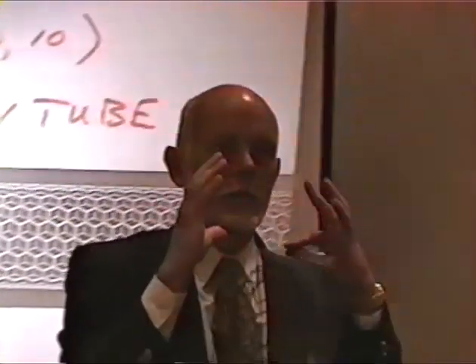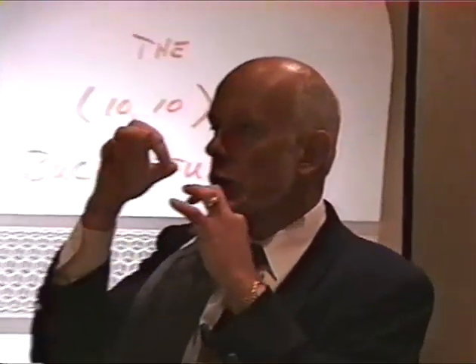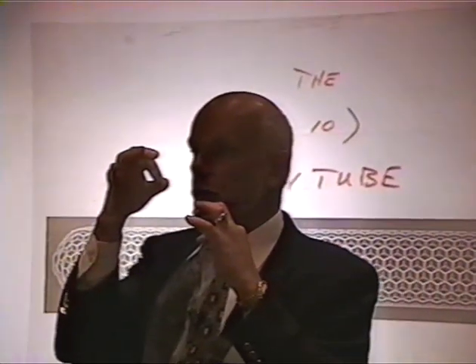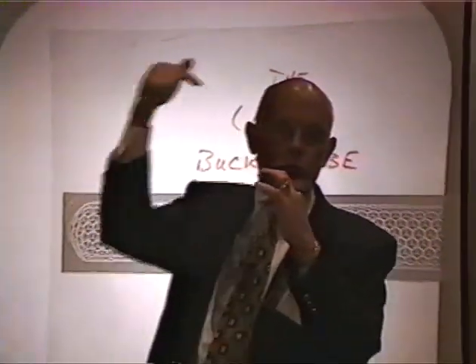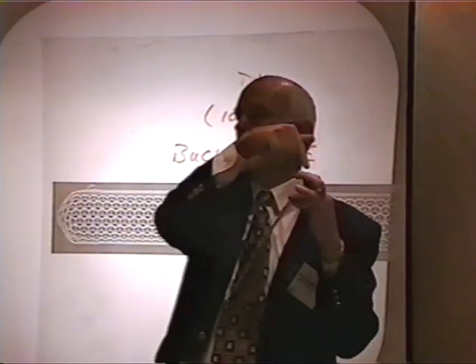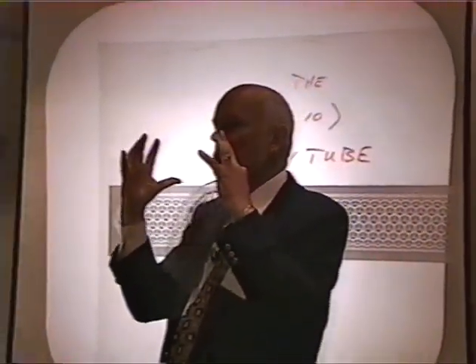C240, in its most energetically favored form, is a round buckyball shape with the pentagons, all 12 of them, separated apart from one another as far as they can possibly be, and that's done with perfect icosahedral symmetry. It turns out to be the next fullerene up from C60 that has perfect icosahedral symmetry and has the same relationship between the pentagons, namely to get from one pentagon to another, you go to a vertex and follow along the bond and you'll find the next pentagon. C240 is the next member up of that family.